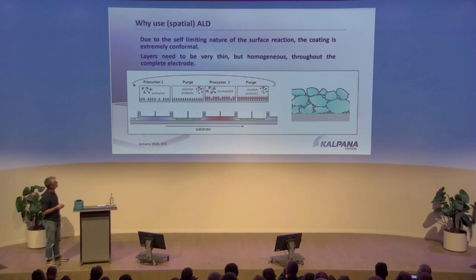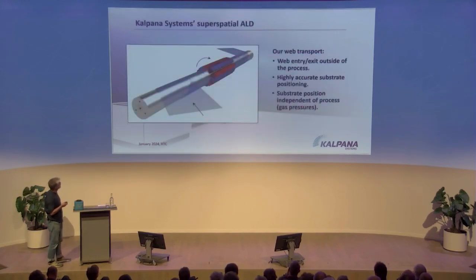Unless you go to flexible substrates, which battery electrodes of course are also. Then you can use a round deposition head, and when you start spinning that, viewing from the substrate, it actually becomes endlessly long. So you circumvent that challenge. But having a flexible substrate, it becomes difficult to control this gap very well. And at Kalpana, we think we solved this issue by doing a few things.